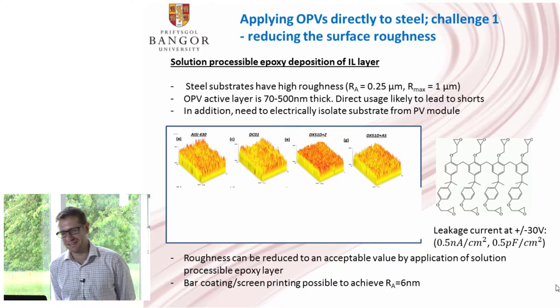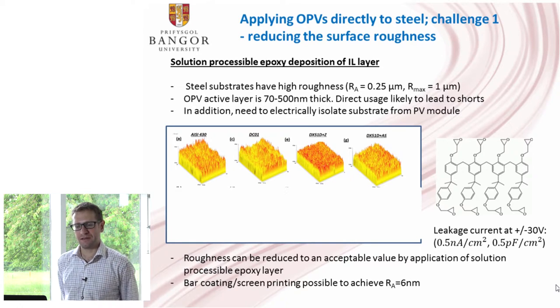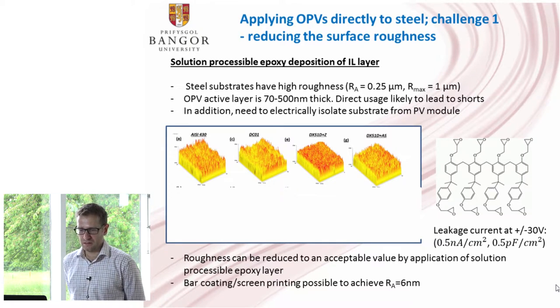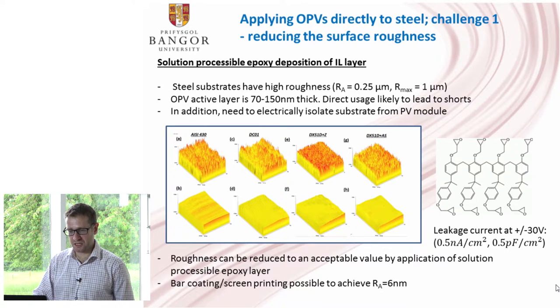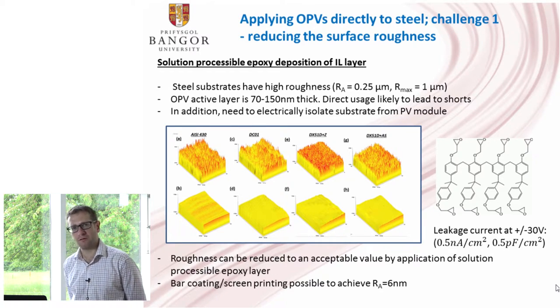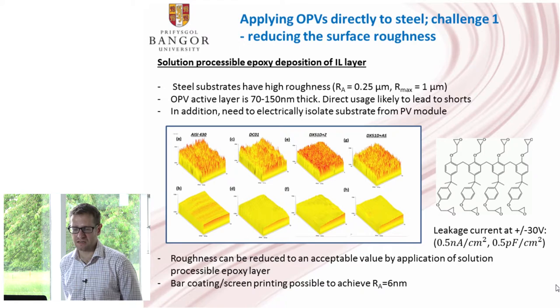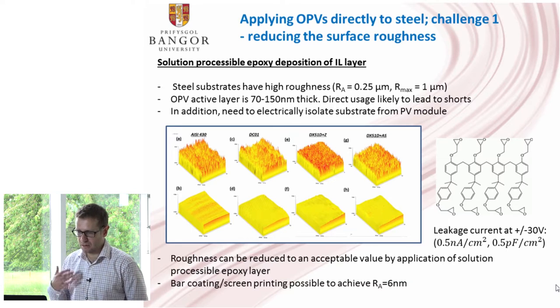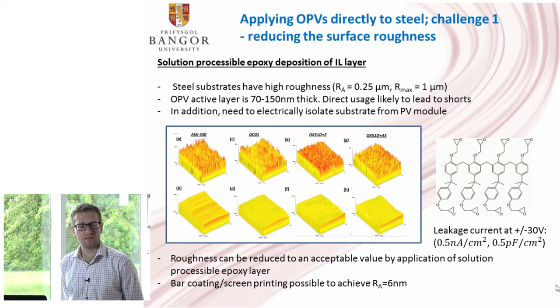Okay, so the OPV active layer is typically from about 70 to 500 nanometers thick. If we try using an OPV active layer directly on a steel substrate, then we're almost certainly going to get electrical shorts. Therefore we apply this epoxy planarization layer onto our steel substrate, and we dramatically reduce the roughness to less than 10 nanometers. So it's almost like a glass-like finish on our steel. In addition, this epoxy-based coating acts as a very good dielectric, so we get very little leakage current from our solar cell into the steel substrate.